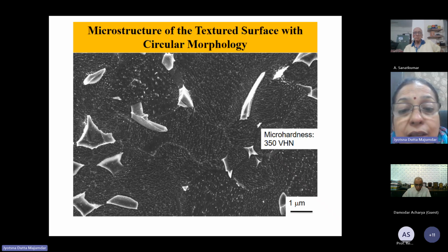So in order to improve the performance further, people use different surface oxidation techniques like anodization and high temperature surface oxidation processing. Here, while processing, we had grain refinement as well as very fine oxide particle dispersion all throughout the surface. These are all beta phases. There was redistribution of the beta phases: in as-received Ti6Al4V, beta is present along grain boundaries, but when we melted it there was vanadium redistribution, so the beta phase was discontinuously present all throughout the surface.